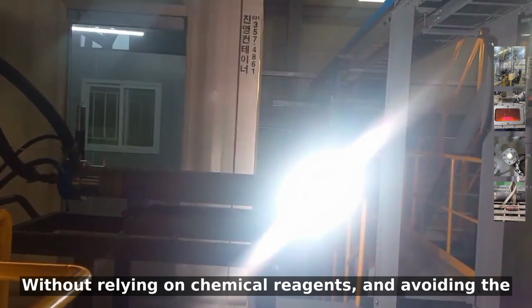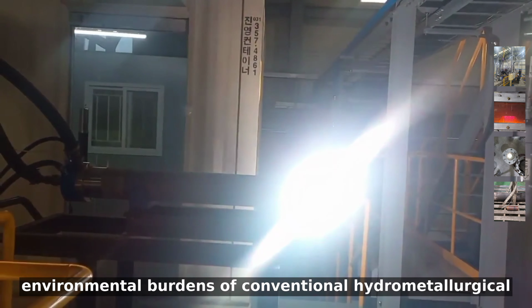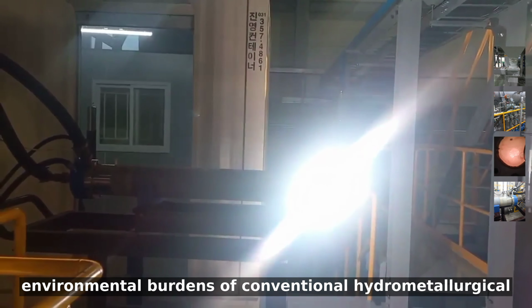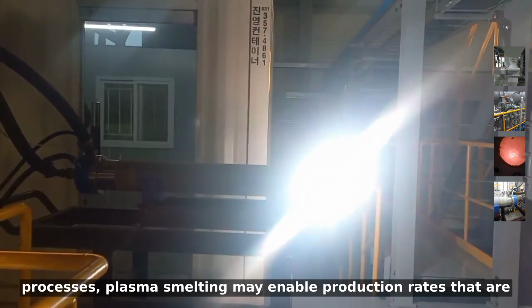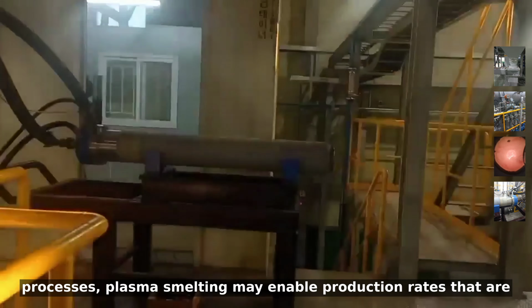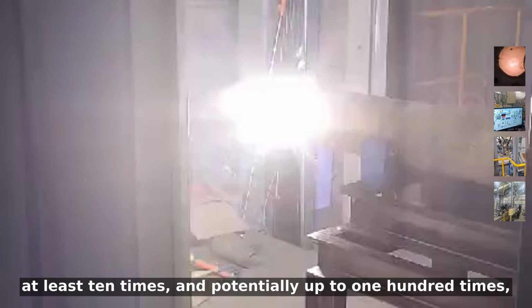Without relying on chemical reagents and avoiding the environmental burdens of conventional hydrometallurgical processes, plasma smelting may enable production rates that are at least 10 times, and potentially up to 100 times, greater within the same operational timeframe for platinum group metals and rare earth elements.